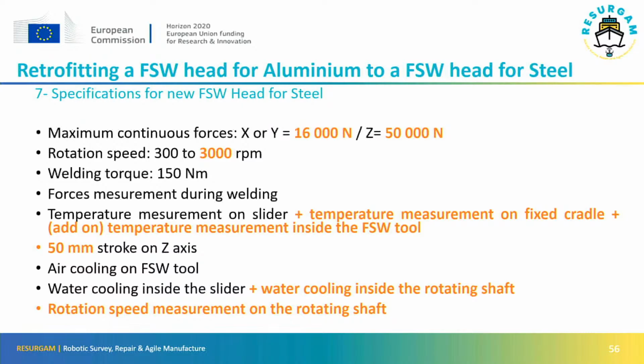So those are the specifications for the retrofit of the FSW head to a steel FSW head. The maximum force on the Z-axis we want to reach is around 50 kilonewtons, and as I said, the X and Y are proportional, so it will be increased also. The rotation speed will be lower than for the aluminum, so we will go up to 3,000 RPM, but the welding torque is much higher, about 3 times the welding torque for aluminum. So it goes up to 150 Newton meters.